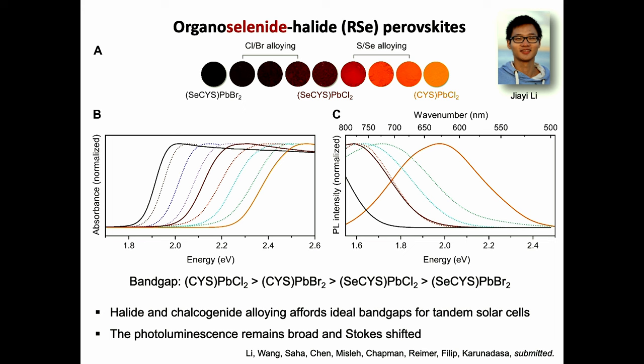So recently, we were able to alloy selenium into these perovskites as well. And now, excitingly, we can mix the chloride and the bromide, but we can also mix the sulfur and the selenium. And this gives us this beautiful range of band gaps that straddle the perfect energy range that we are interested in for tandem solar cells. But again, we still see evidence of this trap state, so our work is cut out for us at this point. We have to identify what this trap state is. Is it a sulfur-rich lead coordination sphere? Is it a halide vacancy? And can we passivate that trap?